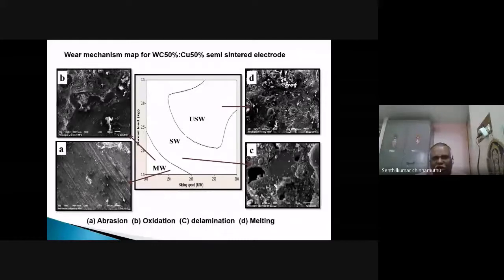So those who want to select a 50% copper semi-sintered electrode, the safest sliding speed is 100 to 200 and the safest normal load is 1.5 to 2.4. That is the safest load, and up to 200 is the safest sliding speed to design a component for a 50% copper, 50% tungsten carbide, semi-sintered electrode.